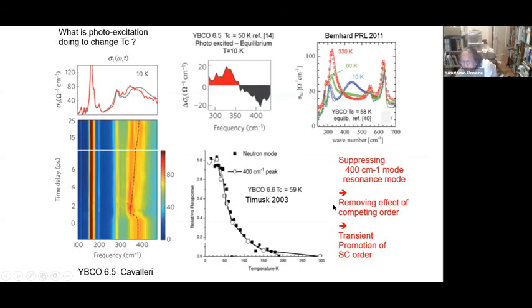Then removing that means removing your competitor, and that may help transient promotion of superconductivity to higher transition temperature, because the existence of the competitor, measured by the resonance mode or maybe the 400 Kaiser mode, is reducing TC.